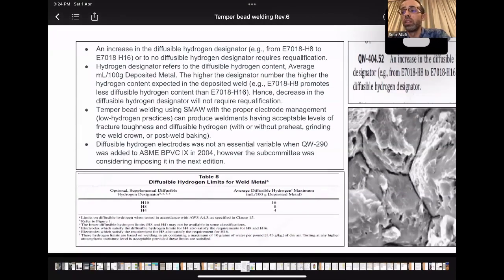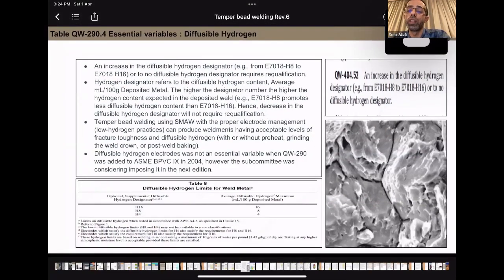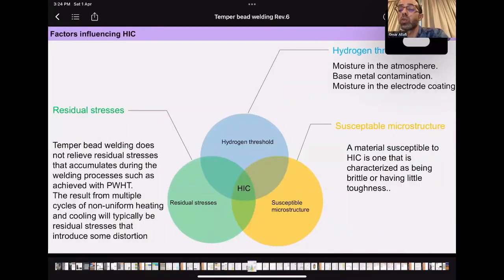So increasing the diffusible hydrogen designator requires qualification, whereas reducing doesn't require any qualification. So if the WPS is qualified using the H8 hydrogen diffusible designator, you can use H4 without requalification, but you cannot use H16 without qualification. Why is diffusible hydrogen important? Because it, of course, prevents against hydrogen-induced cracking. So hydrogen-induced cracking, as we know.